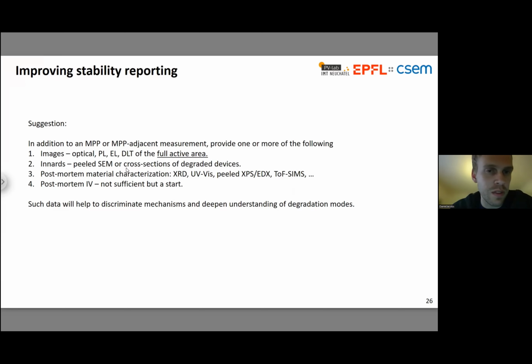I think it would be great if, as a community, in addition to these MPP measurements, we started providing things like images of our degraded devices. Whether that's an optical image or a PL image, EL, or lock-in thermography, of the entire active area, so that we can see whether the degradation showing in the MPP data actually represents something happening uniformly across the device, or whether it's related to edges or particles or something else. I think it would be good if that was part of standard practice in reporting. And I've given a list here in perhaps order of importance.